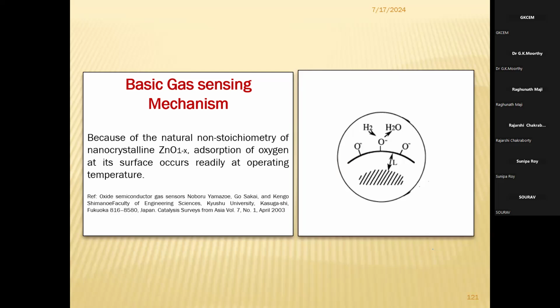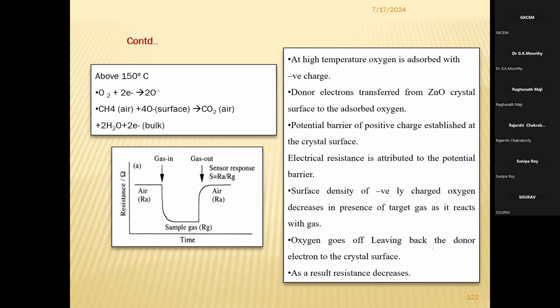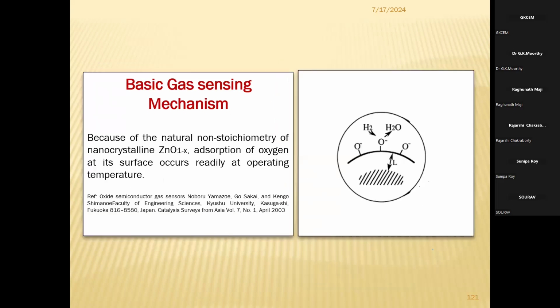When oxygen makes a poor bond with the surface atoms of the sensing layer, oxygen accepts electrons from the sensing layer surface. That's why it becomes O-, and the sensing layer surface becomes positive. So here we can see the poor bond has been established. This bond is called a dangling bond. Actually the sensing layer surface is the donor and the oxygen atom is the acceptor. So this is the donor-acceptor relation. As the sensing layer surface is donating electrons, fewer electrons means resistance is more.